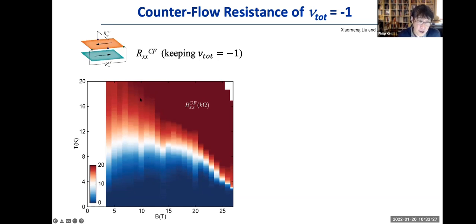If you go to the higher temperature, it becomes finite, you get this normal state, right? So you can clearly see at low temperature, a zero counterflow resistance state shows up. As you go to the higher temperature, it becomes a finite resistance state, which is expected. But what you see here is that as you change the magnetic field, it shows this nice dome-like phase boundary. You now start to see that this dome-like phase boundary is what theorists actually expected to see in the exciton condensation.